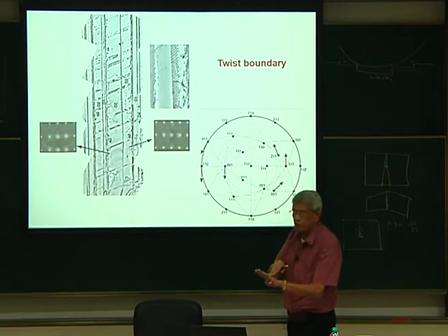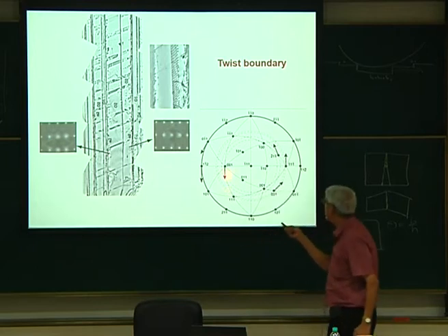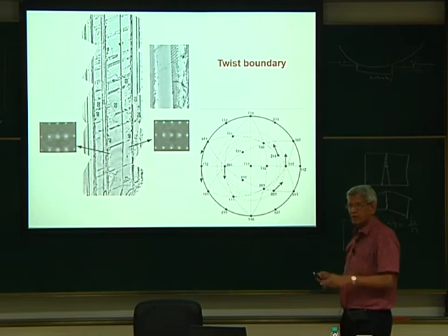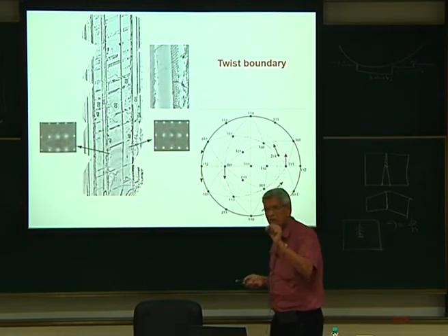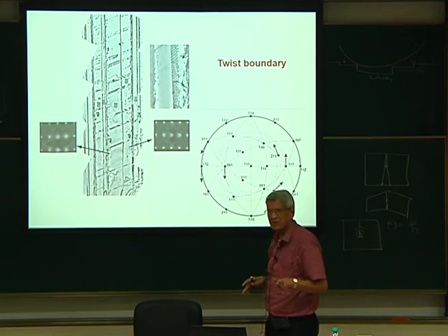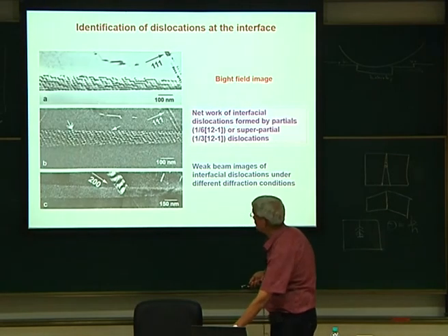Since it is a 111 plane, I have taken a stereograph of the 111 plane and tried to project all the directions, and from this we could calculate, okay, that part I am not going to use. We can find out the exact shift. Here again the twist angle turns out to be 0.6 degree, which is what it turns out from the crystallographic consideration.